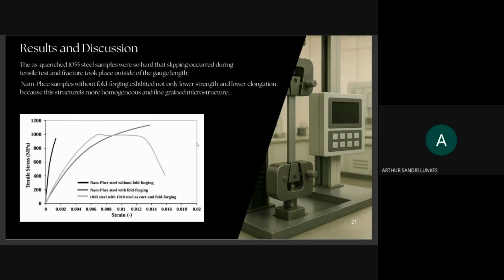Now the authors performed the tensile test. So we can see in this picture here they only have three because the 1055 steel samples were so hard that slipping occurred during the tensile test, and the fracture took place outside of the gauge length. So this problem occurred during the test. So he couldn't finish the test for this sample.